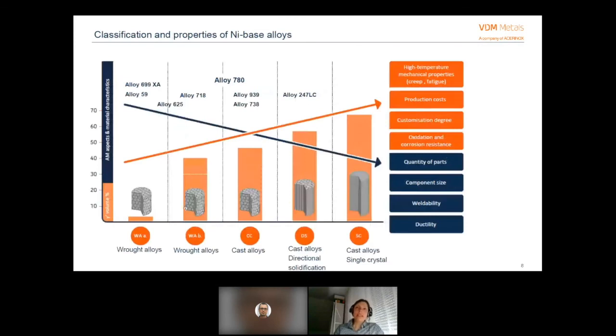So if we discuss the nickel-based alloys, there is really some conflict of interest for the business case for additive manufacturing, from a management or economic point of view, and also a technical point of view. And we can see that with increasing gamma prime volume, so gamma prime is Ni3Al or Ni3(Al, Ti, Nb), the phase fraction is really small, depending on microstructure. We have from 5% or less or nothing up to 70% here. We see that the high temperature mechanical properties like creep and fatigue grow, and the production costs increase or jump high.